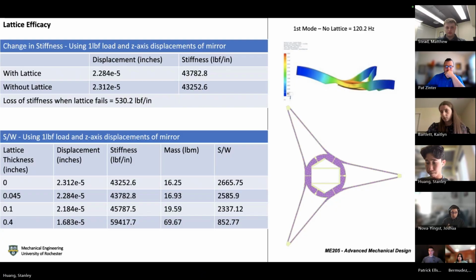We went back and ran some additional simulations to change the thickness of the lattice to see if that could improve the stiffness. It did, but it also drastically increased the weight, and it reduced the part's overall strength to weight ratio. So what we can take away from this is that in this particular case, with this geometry and this orientation of a lattice and this type of lattice, it's not worth it, except to make printing easier, right?